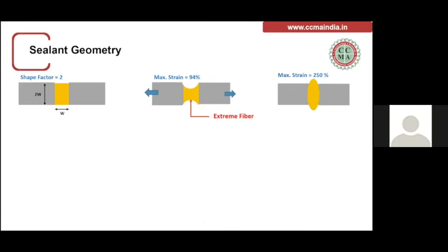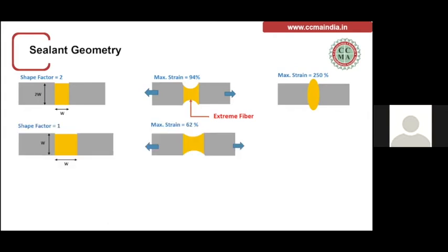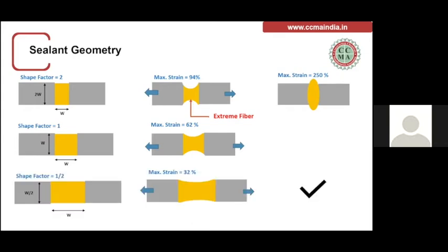And next is understanding the importance of sealant geometry with regard to the performance of the sealant. In case the depth of sealant is twice the width, then the maximum strain is 94% for the extreme fiber in elongation, and it is around 250% for compression. Now, if the depth of sealant is equal to the width, then the strain reduces to 62%. And when the depth is reduced to one half the width, the strain is further reduced to 32%. So we can draw a conclusion that by reducing the depth, you are reducing the strain, and that is why the ideal ratio for sealing is 2:1.